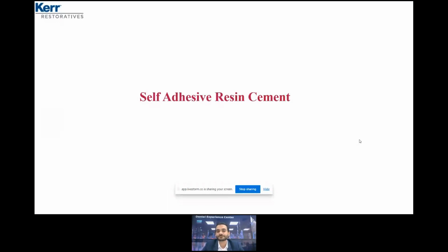Self-adhesive resin cement. As you know, it means I don't need to etch and bond to the tooth structure, because it is self-etch, self-adhesive. But from my perspective, it is recommended to treat the restoration in order to increase its surface area and enhance the bond strength. I know some doctors use self-adhesive resin cement without any treatment of the restoration. It's okay, but according to the newer articles, it is recommended to make a surface treatment also for self-adhesive resin cement, not for the tooth, but for the restoration.